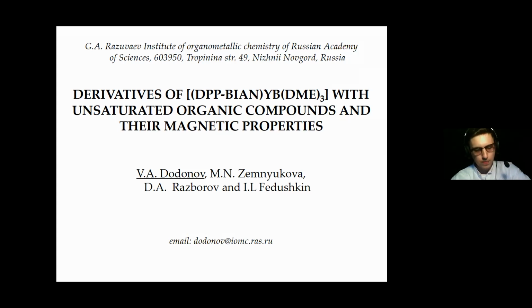Okay. But it should be very interesting because you have very unusual environment around your ytterbium compounds, and sometimes your trivalent lanthanide is associated to a radical, and so exchange interaction could suppress the quantum tunneling of the magnetization that we have often in case of terbium compounds. So I think you have very nice compounds in your hands to have very nice dynamic properties. Yeah, exactly.